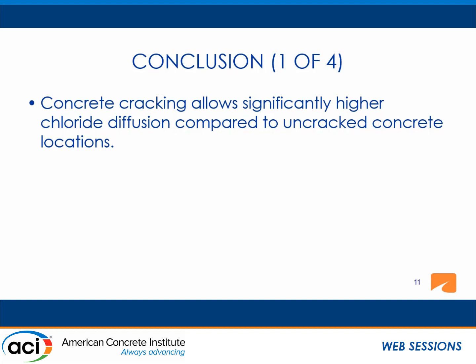Cracking does allow significantly more chloride to diffuse, not necessarily initiate corrosion right there, because it's a probabilistic process. So the same amount of chloride at one point may not be considered a threshold value for the other location, even in the same deck.